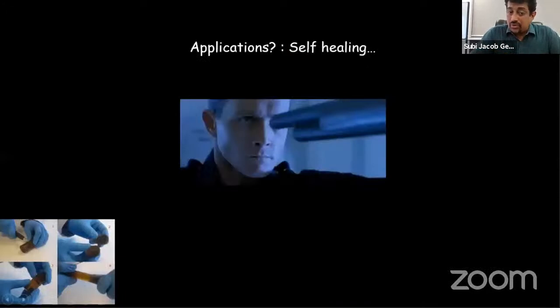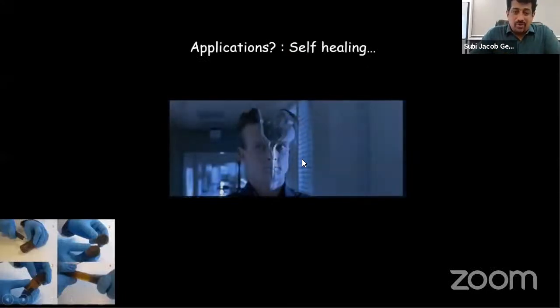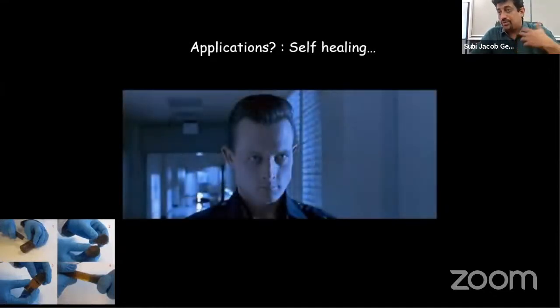This was well addressed, and people have shown that these materials have interesting self-healing properties. All of you know this movie. We always realize that self-healing is really powerful. If you have damage in your material, it can come back and heal itself. These supramolecular polymers have shown enough mechanical properties, some of these ureidopyrimidinone moieties, similar to classical polymers. In addition, the dynamics, which I mentioned in an earlier slide, helps them self-repair. If there is a cut or damage in the material, the dynamics of the monomers going out of the polymeric chain will help them self-heal. These were the initial studies, and people realized these are wonderful materials that can be made completely reversible. If you apply temperature, you can break them because they are weak interactions. Probably we can use them as adaptive and self-repairing materials.